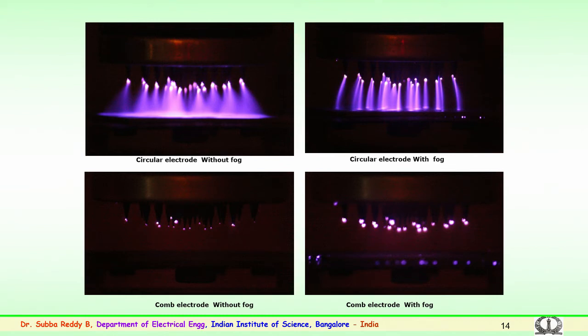During experimentation in normal ambient light, it is very difficult to capture the corona discharges which are impinging on the sample, so these could not be taken with normal photography. The discharges which you are seeing here were taken with a setting of 30 seconds. The ambient is made completely dark and the photography is taken with a shutter speed of 30 seconds, so that you can capture the discharges. During normal conditions, these discharges will not be visible. You can see the corona electrodes of a normal uniform type here. Very clearly, all the 33 needles, where you see the discharges, are impinging on this sample, the polymer sample here.